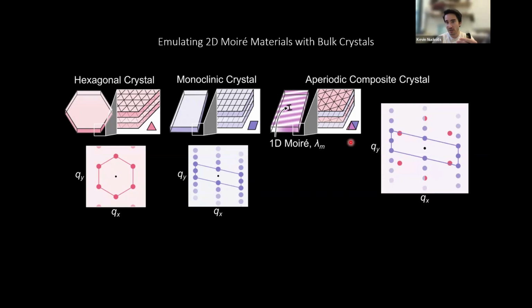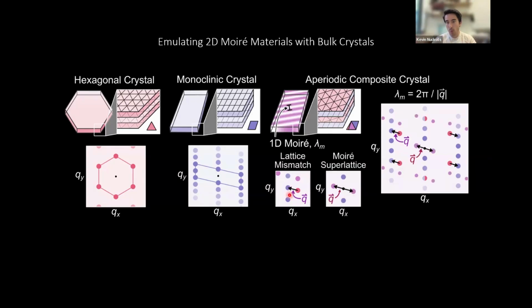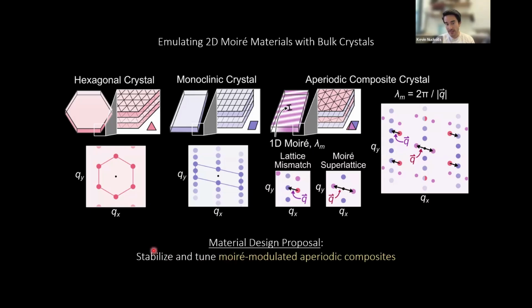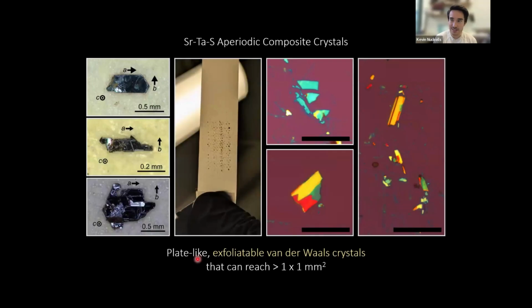There will also be two key signatures that we should look out for to identify Moiré superlattice versions of this. The first is, because these systems have very similar lattice constants, we'll be able to see a small wave vector in momentum space Q that separates the two Bragg peaks, essentially a Q vector that goes from the hexagonal lattice to the monoclinic lattice, because they're not quite commensurate with one another. They're not quite on top of each other. There's a small lattice mismatch. Furthermore, this small lattice mismatch will seed a long wavelength interference pattern, which we call the Moiré superlattice, which we'll be able to see directly in diffraction. This gives us really clear observations of what we should expect for a Moiré modulated aperiodic composite crystal, and we'll in turn try to stabilize this type of crystal, but also try to tune its structure using solid state chemistry. So without further ado, let's jump into some of these crystals.